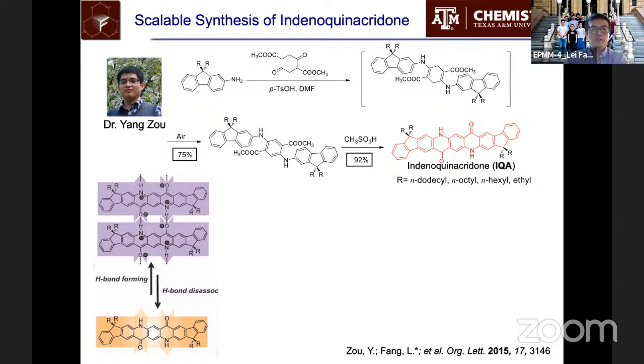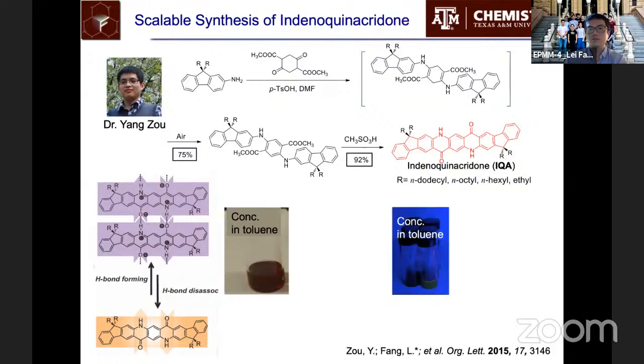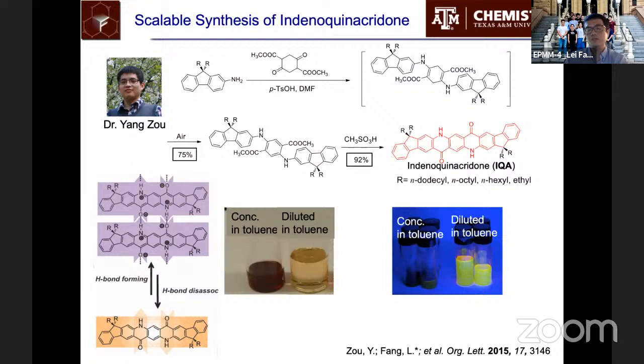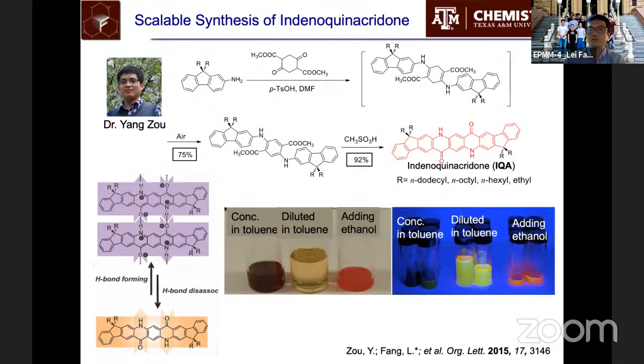Once that forms, it will be non-fluorescent and have a purple color, but you could dissociate this hydrogen bond and then lead to an orangish color while strongly fluorescent. So this way you can see that, for example, if you dilute the solution, you would turn on the fluorescence, or if you disrupt the hydrogen bond, it would turn on the fluorescence. And this kind of aggregation and dissociation could also be triggered using heat, so that at a high temperature, you'll see an increase of the fluorescence and a change of the color.